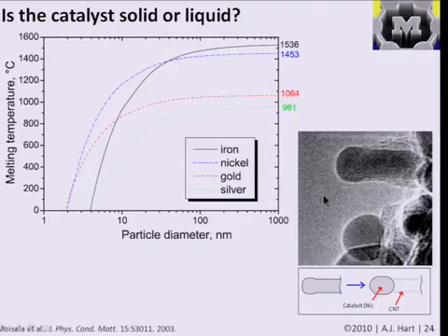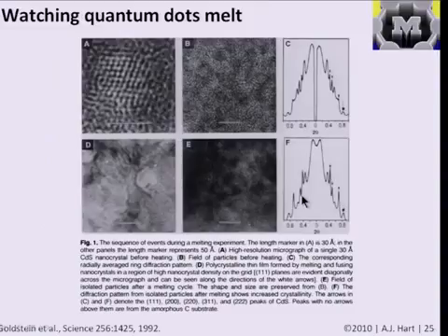And also, the atmosphere is going to make a difference. For example, whether you have hydrogen on the surface or something else on the surface can modify the surface energy, and therefore can change the values of the parameters that we have in our equation, and therefore change the practical value of the melting point. But the thing I want to go home with today is to just realize that there is this significant suppression, and that it depends on the bulk characteristics of the solid and its size, and can also depend on the environment.